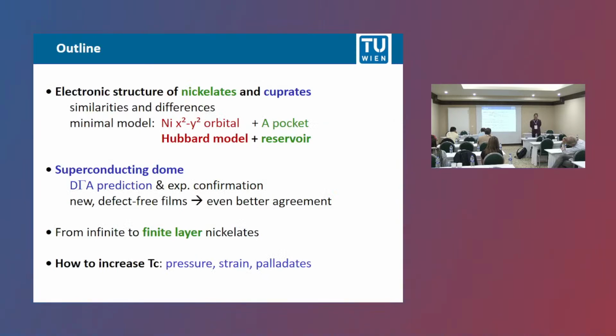The outline of my talk is as follows. I will start with the electronic structure and the ab initio calculation, density functional theory and dynamical mean field theory, and then I will arrive at this simple minimal description with only the x squared minus y squared correlated orbital and the largely decoupled pocket, in particular the A pocket. Based on this simple description, we have then calculated the superconducting dome at a time where only two experimental data points at 20% doping were available by Harold Wang and Ariando. And we predicted the whole doping dependence when we only had 20% doping.